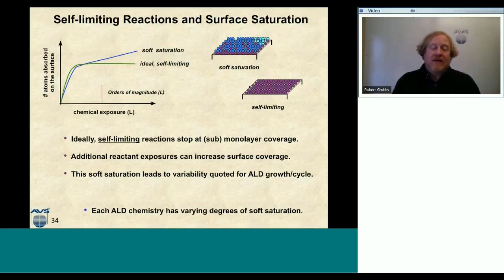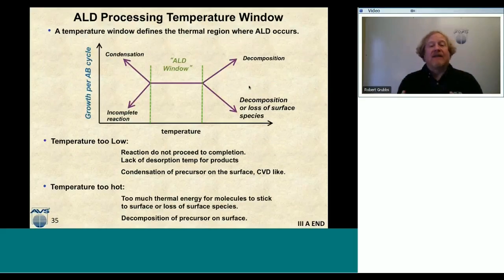So let's talk next about this ALD temperature window. So ALD doesn't exist at all different temperatures. There's a certain window of temperature for each unique process where this ALD chemistry can take place. So here I have on the y-axis this growth per cycle, and the x-axis is temperature. So when the temperature is too low, we can see one of two things occur. We can either see that the growth per cycle actually goes down, or the growth per cycle actually will go up. So these are two different scenarios that happen on the surface.